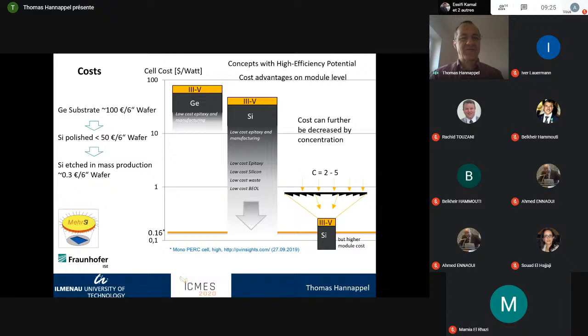You see costs coming from germanium substrates, with €100 per 6-inch wafer, that need to come down to costs which are really orders of magnitude lower. Now, this is something which we have been tackling for a long time by going for III-Vs on silicon. This is also a challenge in terms of science, and the scientific difficulties of doing this without losing the performance of the III-V layers by creating a lot of defects.